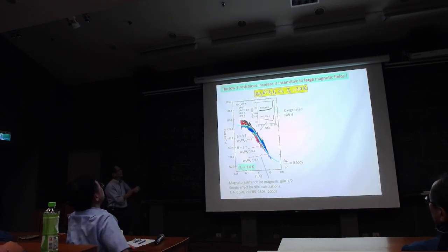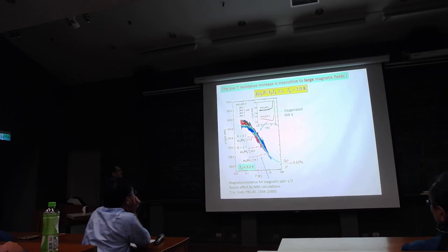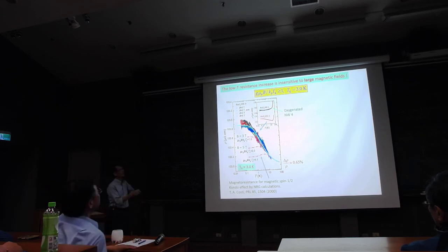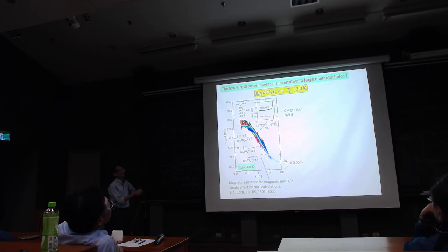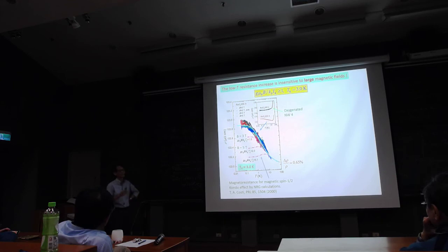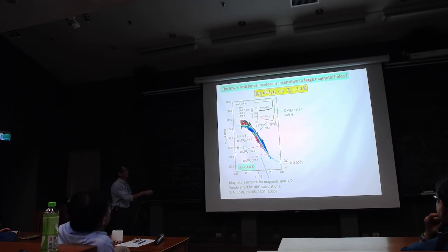This is also a ruthenium dioxide nanowire. I guess this curve is even more beautiful. In this case, we tried to find a nanowire with a very low Kondo temperature. And so if you apply a magnetic field, 3 tesla or 5 tesla, this Zeeman energy is already larger than the Kondo energy. So if this field is large enough, in principle, if your Kondo effect is due to a spin impurity, then you should completely suppress the resistivity increase. And these are theoretical calculations, that curve, that curve. But what we observe is that it all overlaps together.